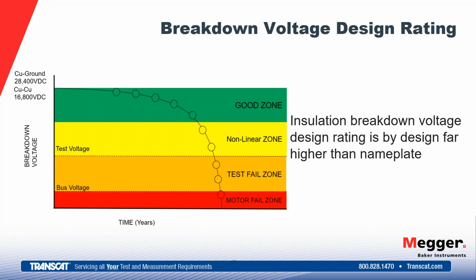So it's well controlled and regulated, so it minimizes any potential carbonization of that motor, thus preserving the option to continue operating the motor. Again, if the insulation is degraded, high voltage testing may take away up to one startup cycle. Realize that this high pot testing is done at much lower energy than when you hit the start button. If the insulation is good, it will withstand that and report back a good insulation system. Whereas if it's weak, then we're reporting back that you have a less than reliable motor in your service.